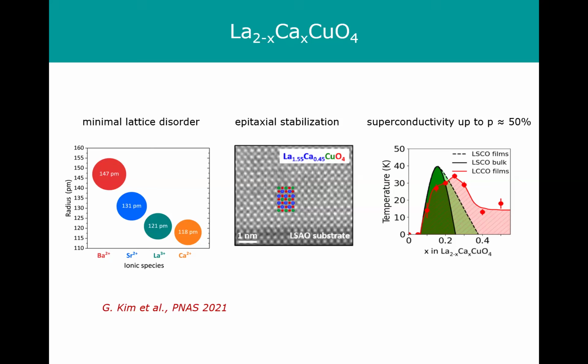When you try to synthesize it with a calcium level of more than, say, 10%, it disintegrates into two different thermodynamic phases. And what Georg Kim here, also working in our institute, realized a few years ago is that you can actually epitaxially stabilize this material by growing it on an appropriate substrate. When he did this, he found that superconductivity is actually stable up to much higher doping levels than in bulk lanthanum strontium copper oxide and also in thin film lanthanum strontium copper oxide, presumably as a consequence of the reduced lattice disorder.